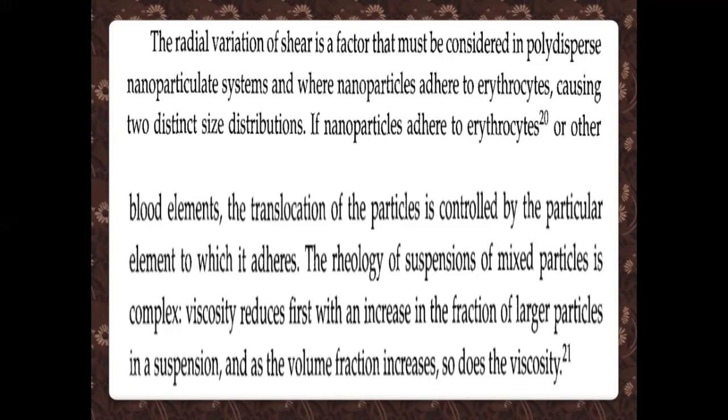The rheology of suspensions of mixed particles is complex. Viscosity reduces first with an increase in the fraction of large particles in a suspension, and as the volume fraction increases, the viscosity also increases.